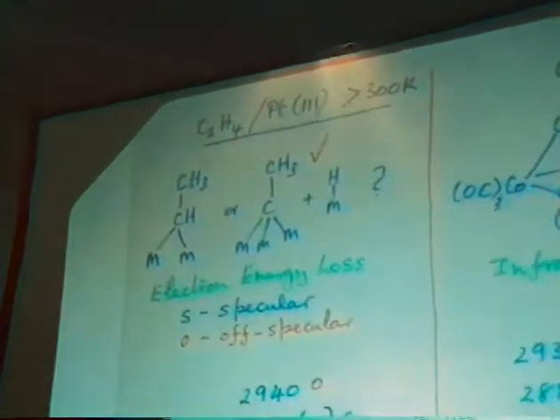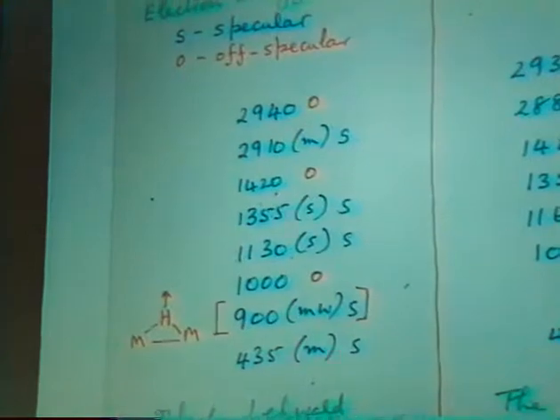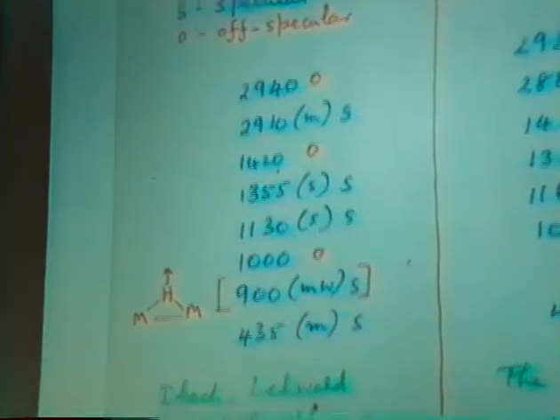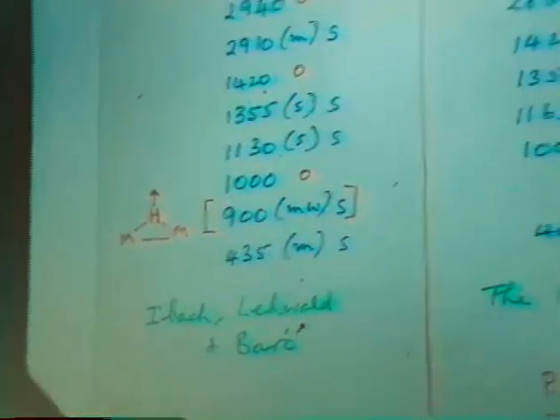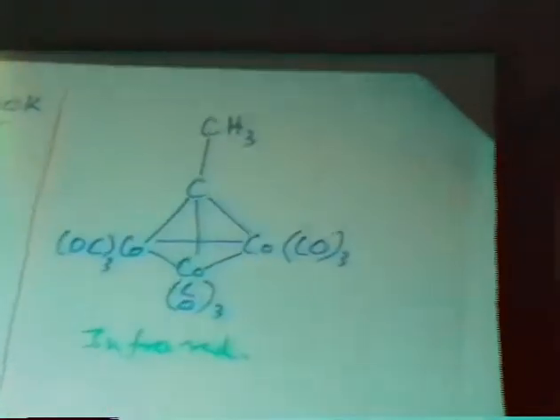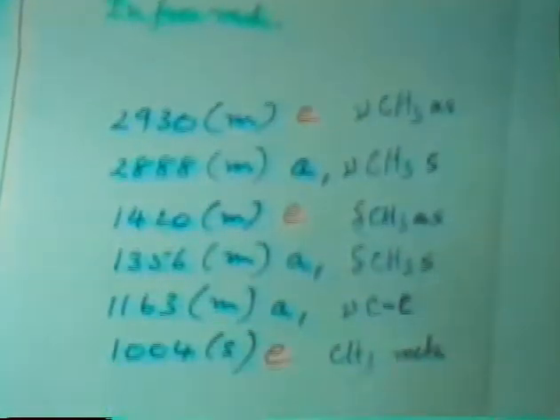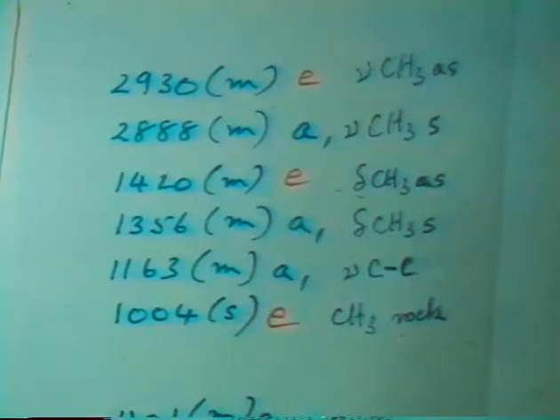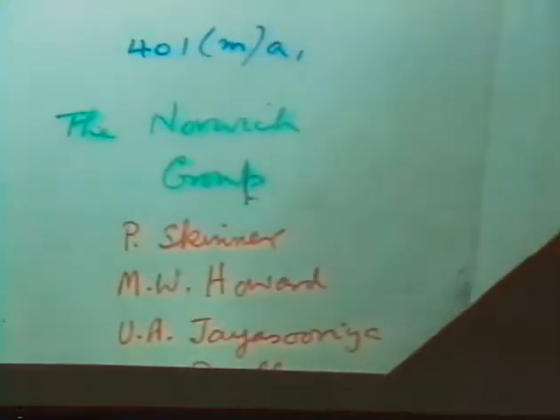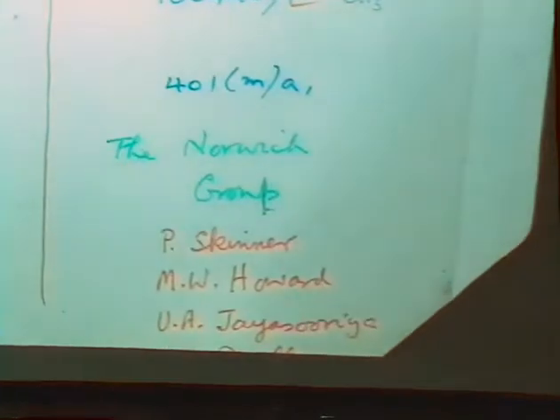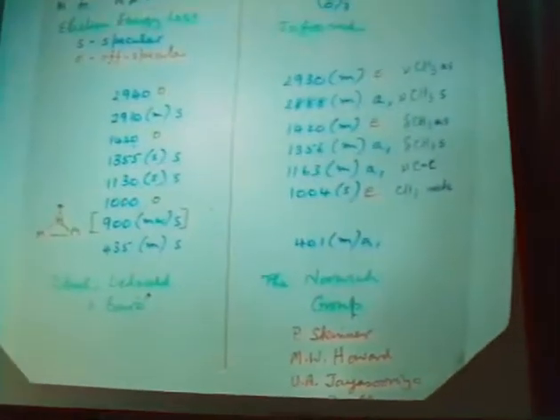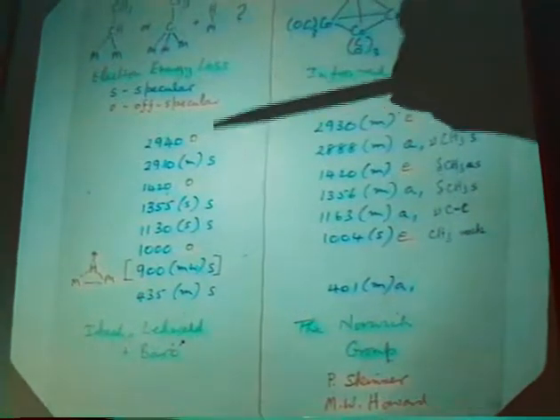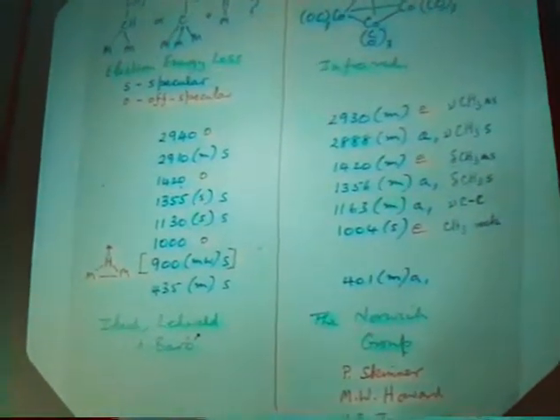My colleagues in Norwich and I wrote to Professor Ibach and said, well, we think it's this species, ethylidyne rather than ethylidene, and these are what we think the frequencies are. Of course, some of the frequencies you won't see on the surface. And he wrote back and said, well, as a matter of fact, we've just taken the spectrum off specular, and we found such different frequencies, we were wondering whether we were looking at a different species. You've given me a list of them. And so, indeed, off specular, they were picking up the parallel modes as well. And I think that was the first species that was really tied down on a metal surface with little ambiguity.